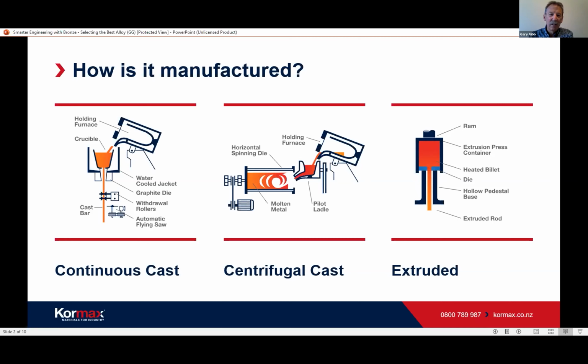The second one is centrifugal cast. Once again, there's a holding furnace where we melt the metal at around about 1200 degrees Celsius. And the metal is poured through a pilot ladle into a rotating steel die. The die is rotating at around about 600 RPM, give or take 100 either side, depending on the diameter. And it spins until it freezes, and cooling water goes on the outside of the steel die.